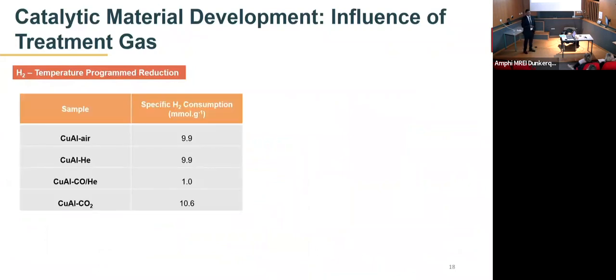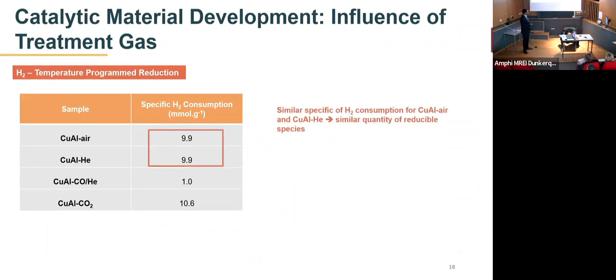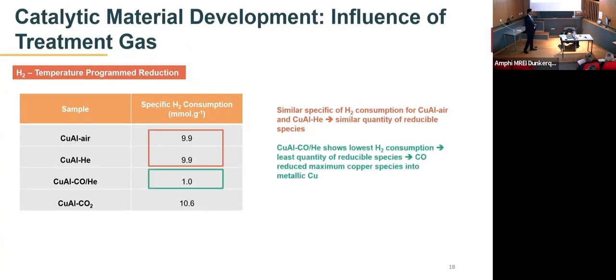The next part of the H2 TPR analysis that we studied was the specific hydrogen consumption during the analysis. We saw that the air and the helium treated samples show a similar specific hydrogen consumption, which means they have a similar quantity of reducible species in the material. For the carbon monoxide treated sample, we see the lowest hydrogen consumption, which is again associated with the formation of metallic copper that we already saw in the XRD. So we don't have a lot of reducible species available in our material, and therefore we don't have a huge amount of hydrogen consumption during the analysis. The last part is the carbon dioxide treated sample, which shows the highest specific hydrogen consumption of all the other samples.